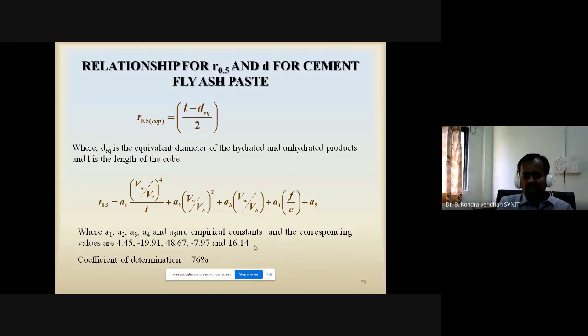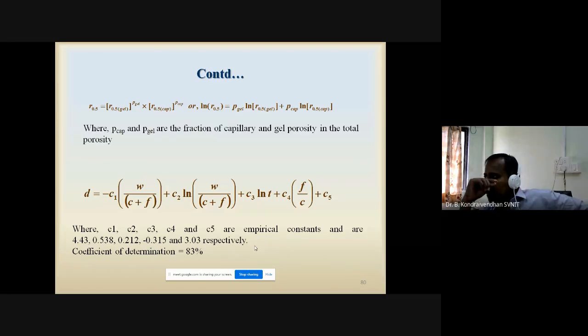So here again, initially we tried with the water cementitious ratio like W by C plus F, but that is not fitting well. That's why we modified, and we came to know the volume of water to the volume of binder is fitting well. So instead of water binder ratio, we use the volume of water to the volume of binder ratio. That's how we got this kind of relation for the R.5 gel entry radius. So finally, we got the overall R.5, the same formula I proposed in case of OPC paste. Similar kind of relation we got for the cement fly ash paste also.